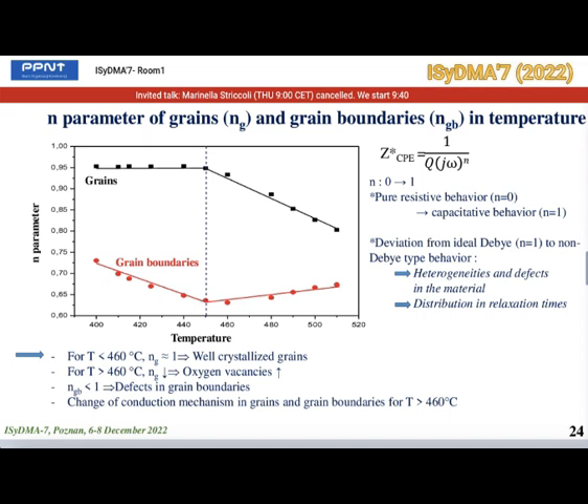On the curves, we can see that for T lower than 460 degrees, Ng is near 1, indicating that the grains are well crystallized. For T higher than 460 degrees, Ng decreases. This is probably due to an increase in oxygen vacancies.